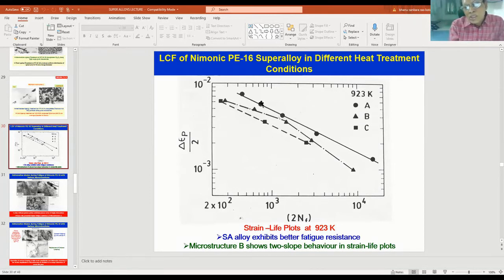If I conduct my tests at high strain amplitudes and try to extrapolate to the service conditions, which take a very long time to test, we have to apply low strain amplitudes. If I try to extrapolate the high strain data to low strain levels, I will be making a mistake. If I take the high strain data and extend it like this, the curve will be like this, and I would say that the peak-aged alloy will give better fatigue resistance. But actually, that is not the case. When you go to low strain amplitudes, your fatigue resistance is decreased. So it is very important for you to know what is happening during service at low strain amplitudes and other conditions. That is where the strengthening mechanisms come into play.